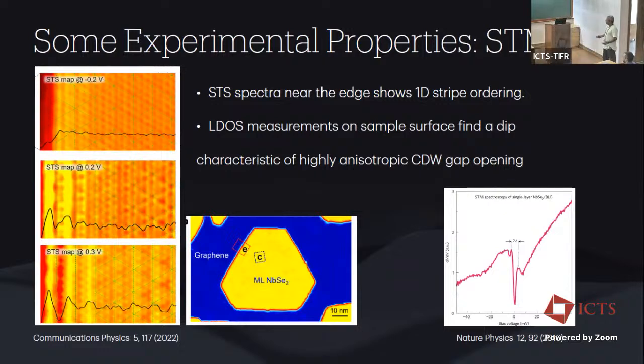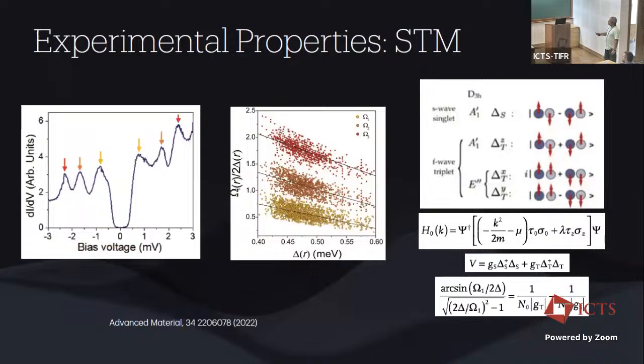Okay, so that's one. Now, for the superconducting state, this was one of the papers in 2022 which generated quite a bit of interest. And this was, again, an STM measurement, where they looked at the local density of states in the superconducting state, and they essentially found evidence of the presence of collective modes or Leggett modes in the superconducting state. And they did an analysis based on the higher harmonics of the Leggett mode and found that there is an anti-correlation between the evolution of the superconducting gap and the energy corresponding to the Leggett mode.